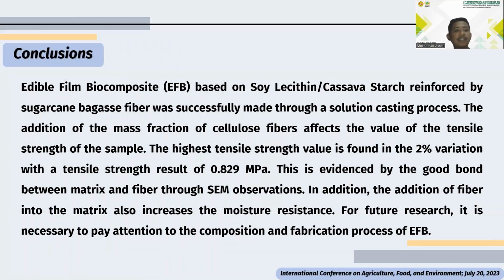So from all of the analysis, we can conclude that the edible film biocomposite, based on cassava starch and lecithin, reinforced by sugarcane bagasse fiber, was successfully made through the solution casting process. The addition of mass fraction of fiber in the matrix affects the value of tensile strength. The highest tensile strength is found in the 2% variation with a tensile strength result of 0.829 MPa. This is evidenced by good bonding between matrix and fiber through SEM observation. In addition, the addition of fiber in the matrix increases the moisture resistance.